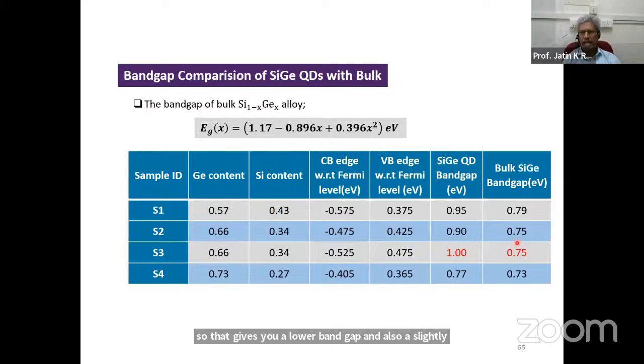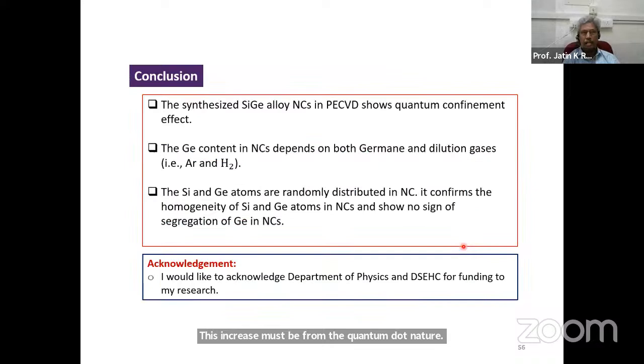And we considered the bulk silicon germanium band gap. If you take that much germanium content, it should be around 0.75 electron volt. But with our measurement from the STS, it gives 1 electron volt. That means this increase must be from the quantum dot nature. That's because of the quantum dot nature, the optical band gap increases.